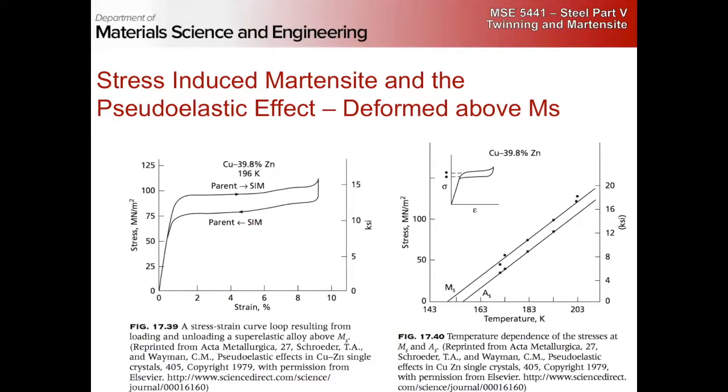Here we're saying, whether you have a huge amount of driving force, whether you're really below the martensite start or you're just a little below the martensite start, the growth kinetics are the same, right? I guess that would be the analogy that I would make with twinning there. Okay.